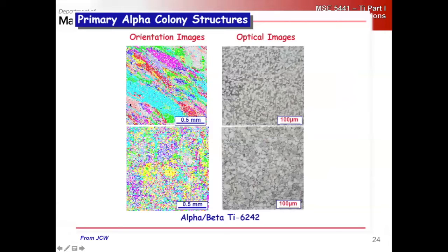And so essentially this acts like one gigantic large grain, right? If you now have a hard orientation next to a soft orientation, you have a stress concentration and a crack path that can essentially grow unimpeded across the big thing. And if you think about what the critical crack size is, the critical crack size in a part is going to be less than the size of one of these big microtextures, right?